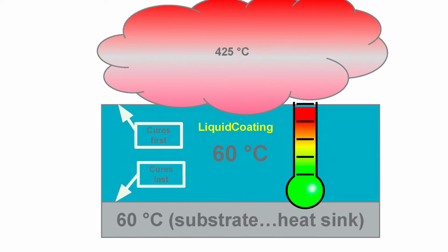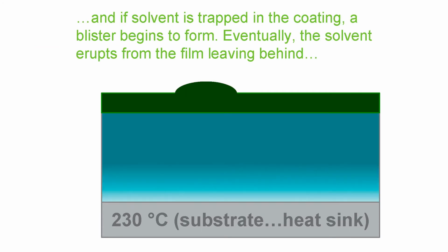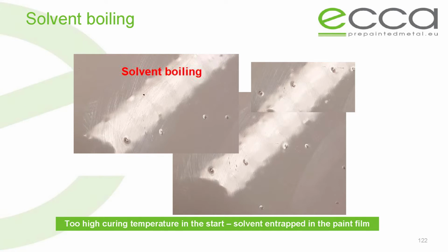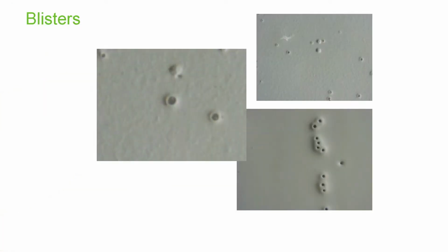So here I'm just showing that you've got hot air, cool metal, cool paint, and with time, the metal starts heating up. And if you've got solvent trapped in the coating, and if the coating begins to cure on the top, but you still have some solvent that has to evaporate, you start forming at least the possibility of a bubble. Now, this may sound crazy, but I can't tell you how many months of my life I've been on coil lines trying to overcome things like this, whether you call it solvent popping or solvent boiling or blisters. Basically, it's all the same thing.